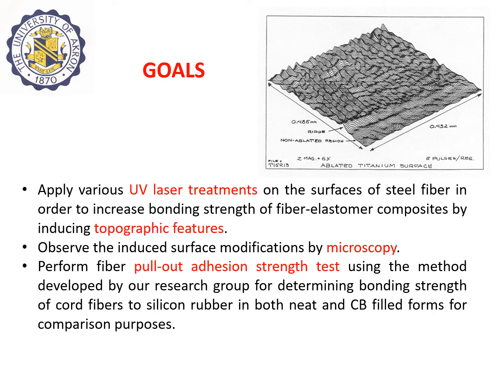Our goals involved applying various UV laser treatment on surfaces of steel fiber in order to increase bonding strength of fiber-elastomer composite by inducing topographic features. For example, on upper right here, I show Excimer laser-treated titanium surface which acquires rippled wave-like surfaces. We then would like to observe the induced surface modifications by microscopy.